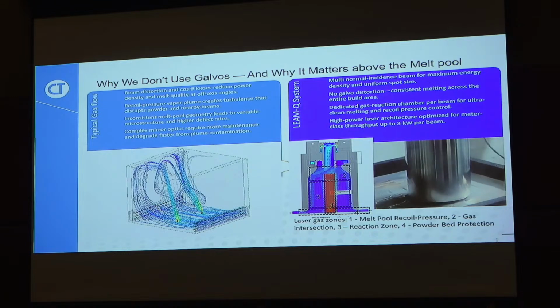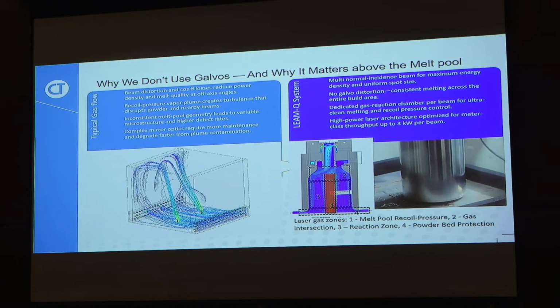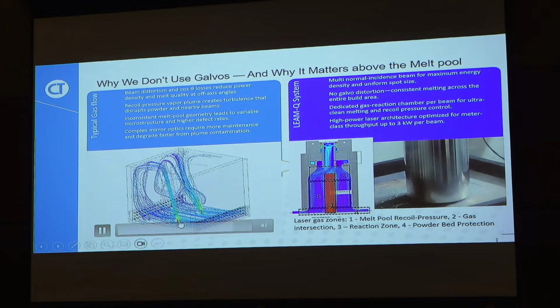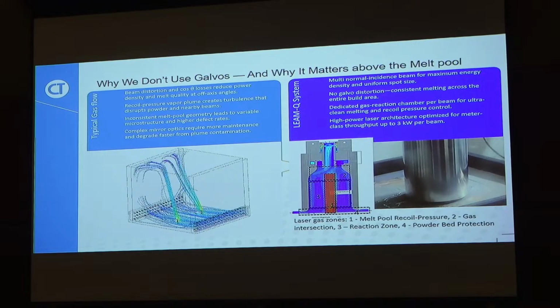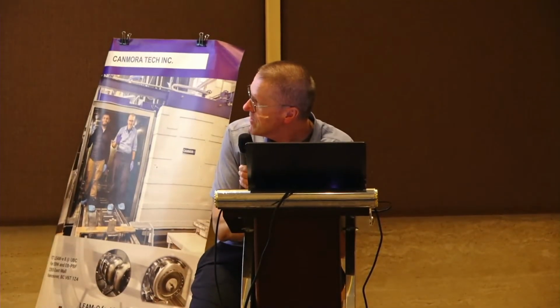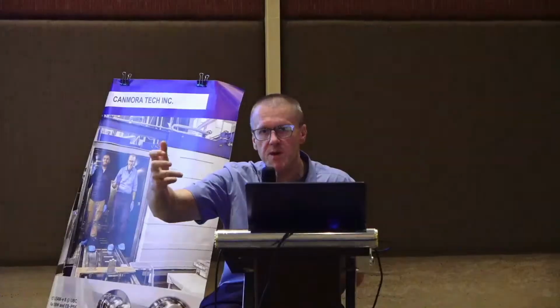So again, the left side is your standard galvo-driven system, okay? Let me just get the mouse here. As this gas, the inert gas protecting the powder, moves across the surface, this plasma shoots up, okay? And then the gas hits the melt pool, and behind that there's a low pressure region, you can model that actually. That low pressure region causes a lot of problems, and it makes a chaotic gas flow in here. And you can see that if you look at the standard machines that use galvos and go in large angles, you can see a lot of these black soots sometimes coming out, right? And depositing dark particles over the surface.